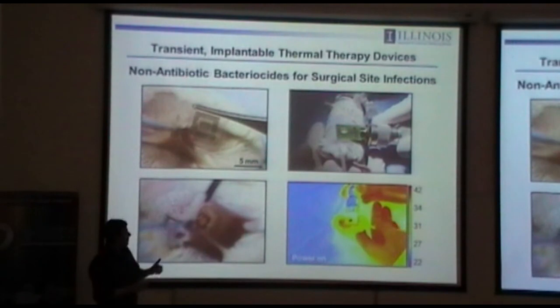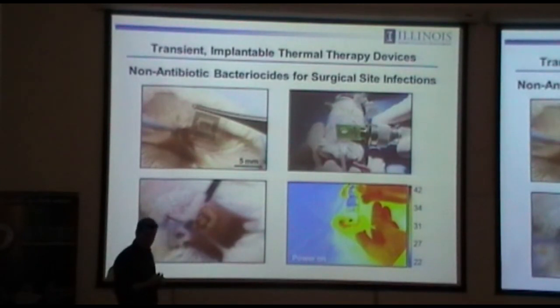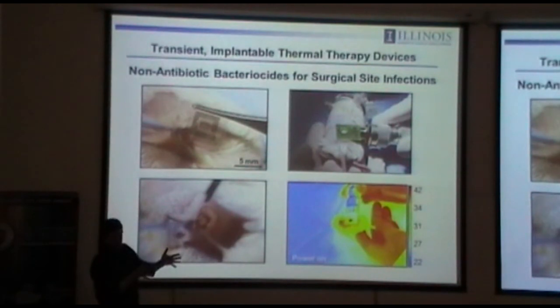And it turns out that for this readmission into the hospital, that most critical period is about 2 weeks after the surgery. Beyond that time frame, the surgical site wound is typically healed sufficiently that the incidence for an infection is much reduced. And so you don't really need the device longer than about a 2 week period. And in fact, you'd like the device ideally to simply disappear. Otherwise, it just represents unnecessary device load in the body. And that's exactly what we configured this device to do.